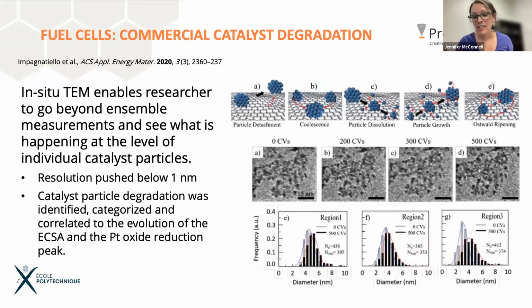And then finally, this is just an example of a commercial fuel cell catalyst called Tanaka TEC 10V50E. These are really small particles, 3 nanometer size platinum particles. And again, trying to understand the pathways of electrocatalytic activity degradation, essentially. And this usually comes as the particles enlarge, because now you are losing surface area of having tons of small particles. As you lose surface area, you're going to lose catalytic activity.